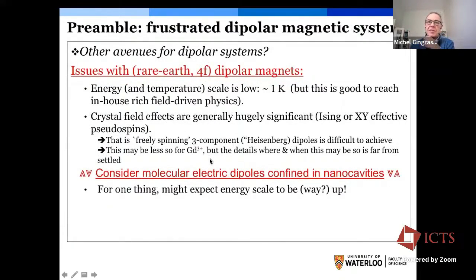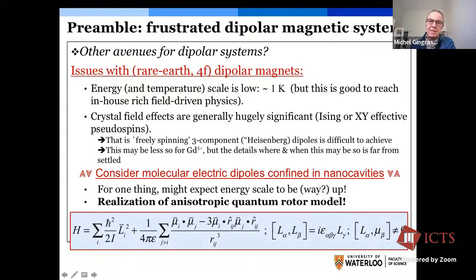So the idea is to look at completely different systems, and the one that I want to talk about is molecular electric dipoles confined in nanocavities. This is interesting from the point of view of new phenomena, materials, and energy scale, but also because it becomes a realization of an anisotropic quantum rotor model. What we have is an upgrade, if you wish, of the quantum O(N) rotor model that I mentioned in the second slide of the talk, where we again have angular momenta as the single particle term in the Hamiltonian, the kinetic rotational energy, but now our rotors are not coupled by an isotropic O(N) type interaction, but by a long-range dipole-dipole interaction. And the physics operating here, the quantum mechanics, originates from the fact that the dipole operators do not commute with the angular momentum operator.